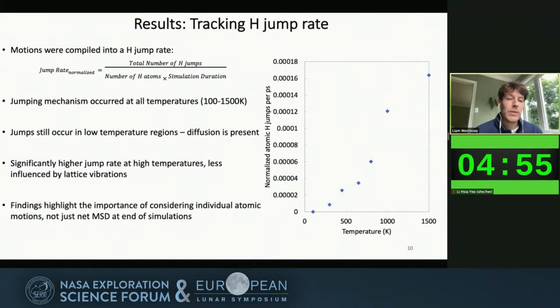What's important to note is that we did observe a jumping mechanism across all the temperatures studied between 100 to 1500 K. Furthermore, and perhaps even more importantly, we did find jumps in those low temperature regions. Because we're seeing jumps from one O to another, this means that diffusion is present at these low temperatures. As we move up to higher temperatures, we obviously see a significantly higher jump rate, which means that the activation energies are significantly less influenced by the lattice vibrations. Basically, what these findings highlight is the importance of considering the individual atomic motion and not just the net MSD at the end of the simulation.